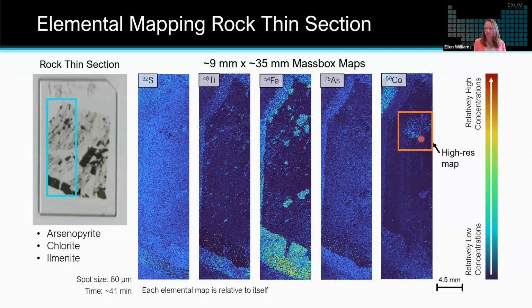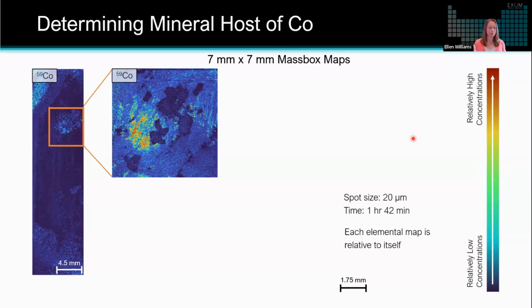So you can see how we have identified this area with relatively high amounts of cobalt, and then we can do a secondary map which is smaller, covers that smaller area of interest that we want to see with a higher resolution. In this case, 20 micron laser spot size. This did take a bit longer, so an hour and 40 minutes, but you can see a much higher resolution picture of how that cobalt is distributed.